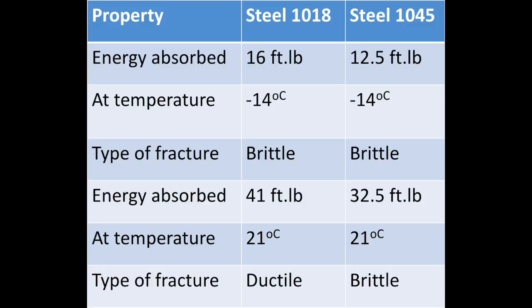The first 2 rows of the results table were done with pieces taken from the refrigerator, as can be seen, at minus 14 degrees Celsius, and there was quite a low energy absorption, and 100% brittle fracture. Then at room temperature, the energy absorption increased significantly, and the 1018 steel presented a ductile fracture as opposed to the 1045 presenting a brittle fracture. In this case, the 1018 still absorbed more energy than the 1045, probably because it has less carbon.